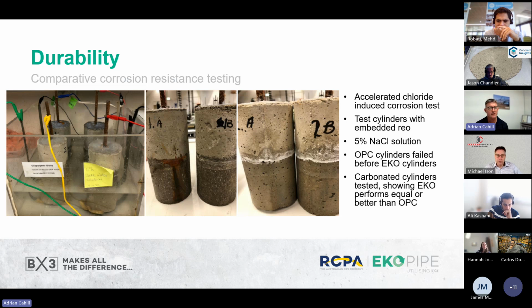We did one where we carbonated cylinders and showed we got the same sort of result. There was definitely a difference in carbonation. The EcoPipe cylinders did carbonate to a higher level, but that didn't translate to any change in the resistance to corrosion of the steel, even under this condition. It's not a standard test method, but it's something that we've done to give confidence that there's no concern. Well, there shouldn't be a concern there.